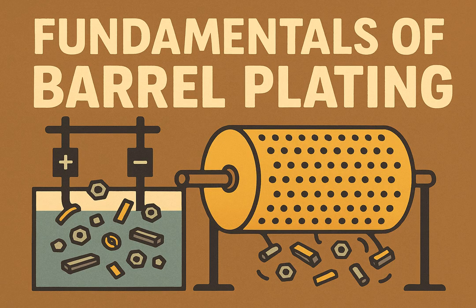And the actual DIY plating step, how does that work? For the plating itself, they recommend using low voltage, even down to around 1 volt, for the best, shiniest results. Higher voltages tend to produce poor, burnt deposits. Lower voltage is better. Interesting. Yeah, for quality in this simple setup. The object to be plated is connected to the negative terminal and the pure nickel source, or another inert anode if you've already made your solution, to the positive.